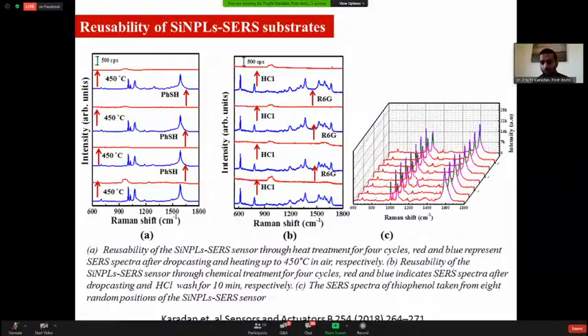We also checked the reusability in a chemical environment. We treated it with HCl, then again recorded the spectra, and we confirmed that it is stable against chemical environments as well. For checking the reproducibility of the substrate, we drop-casted the molecules at some 8 random positions of the substrate and recorded the spectra, which gave almost similar spectra, showing the reproducibility of the sensor.